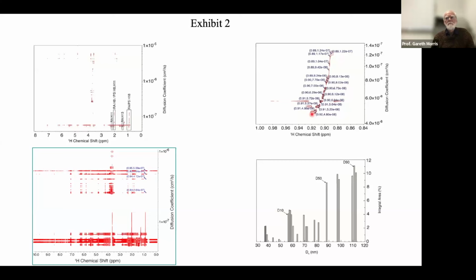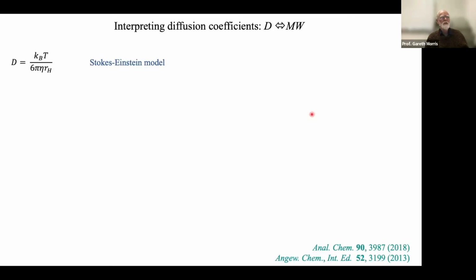I said that the relationship between molecular weight and diffusion coefficient was in some ways an unhelpful one, that a big difference in molecular weight gives us a significantly smaller difference in diffusion coefficient. But suppose that we have a diffusion coefficient and we want to estimate a molecular weight, or suppose we know a molecular weight and we want to estimate a diffusion coefficient. The obvious starting point is the Stokes-Einstein equation, in which we regard a molecule as a ball. Most molecules are a ball to first order.